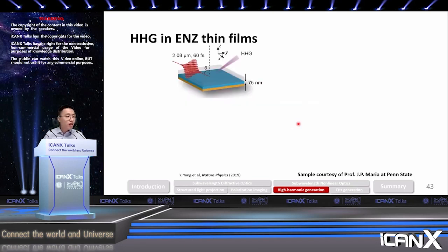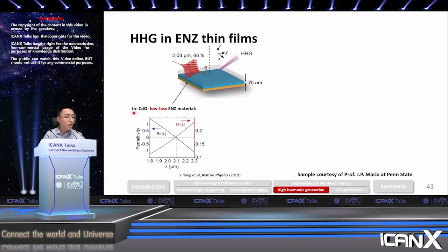So that's where we found that we may have an opportunity to do high harmonic generation, or strong field laser physics experiments, using thin films of epsilon-near-zero material. The particular ENZ material we use is indium-doped cadmium oxide. Cadmium oxide is similar to ITO. It's also a conductive metal oxide, but it has a higher electron mobility, meaning that at its ENZ wavelength it has a relatively low imaginary part of permittivity, which gives us a much higher field enhancement than ITO.